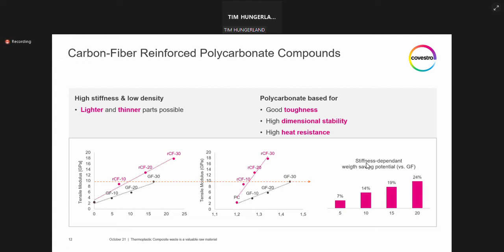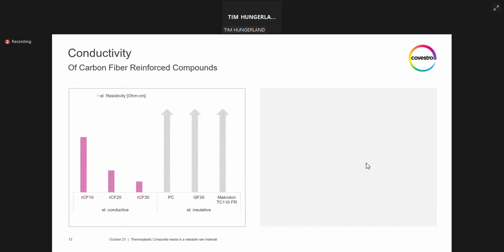And lastly, when making products on the basis of polycarbonate, the polymer itself brings some additional benefits typical for polycarbonate, like good toughness, high dimensional stability of an amorphous plastic, and high heat resistance. But there's more. While unfilled, glass fiber reinforced, or mineral-filled plastics are electrically insulative, carbon fibers add the ability to conduct or dissipate electrical charges. Electrical conductivity is an important ability of the material if your application requires, for example, anti-static behavior or EMI shielding, for example in electrical circuit enclosures.